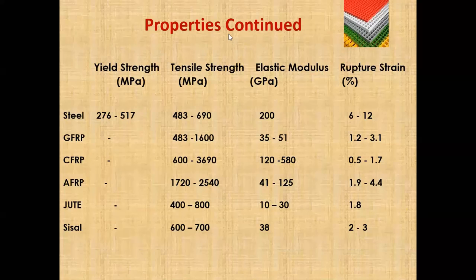The other properties, if you compare these commonly used fibers: the yield strength for steel varies from around 270 plus to 500 plus, whereas the tensile strength is around 480 plus to 690, the elastic modulus is around 200 GPa, and the rupture strain is of the order of 6 to 12%. Whereas for GFRP, the tensile strength is 483 to 1600, the elastic modulus is 35 to 50, low compared to steel, and the rupture strain is of the order of 1.2 to 3.1.